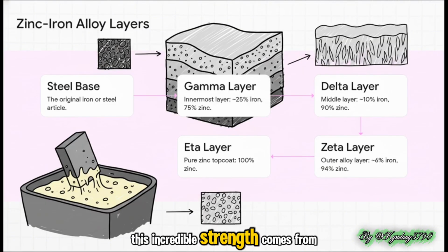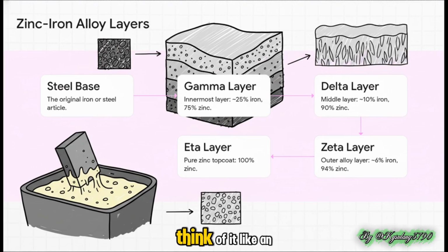This incredible strength comes from a layered structure. Think of it like an onion. Starting from the steel base and moving outwards, the reaction forges these distinct alloy layers. First, you get the incredibly hard, iron-rich gamma layer. Then, the delta and zeta layers, which have more and more zinc. And finally, the outer surface is the eta layer. That's pure zinc, and it serves as the first line of defense.